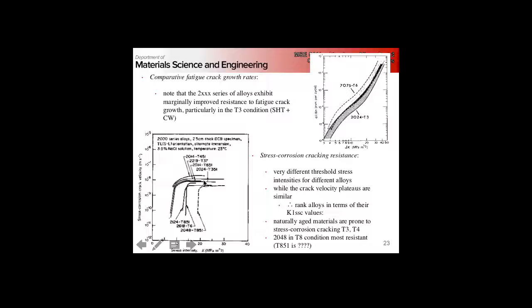So how do we interpret this plateau? If we raise the stress, our crack isn't growing any faster. It's sort of like the steady state crack growth where no matter how high we make the stress intensity or K value, our crack growth stays basically the same. That means we can rank these by their effectiveness to stress corrosion cracking by just ranking their K1 value for stress corrosion cracking.